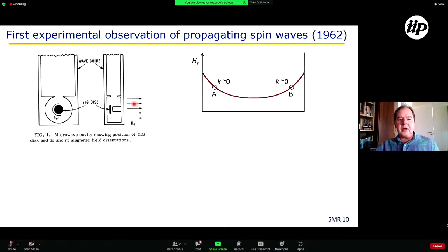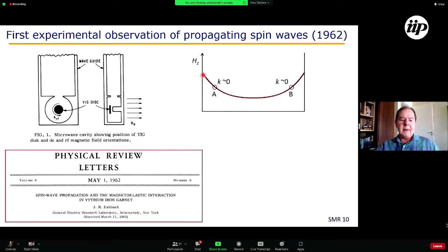So if the field is applied perpendicular to the disk, and if we look at the magnetic field inside the disk, it has this shape here. It has this shape because of the demagnetizing effect, which is larger in the middle of the sample and smaller at the edges because of the form of the surface dipole.